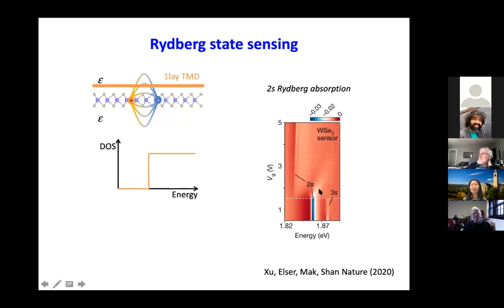So then we did this testing. So we put a single sheet of a semiconductor, a different one, nearby, and then we can dope it using, again, the gate voltage technique. But we only dope the sample, but the probe stays charge neutral. And then you can see what's going on here. It's a 2D sheet. When you dope it, the density function just has a step, right? So this is what we can see in the response of the probe.